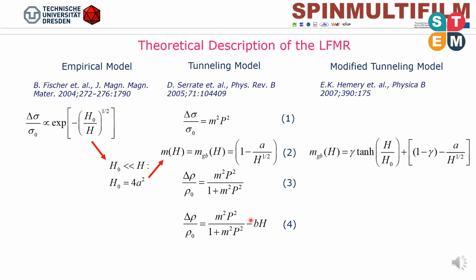Intragrain magnetoresistance is accounted for by adding a linear term, equation 4. This linear term is typically large near the magnetic ordering temperature. In the limit of small fields compared to the magnetic field parameter H sub 0, the empirical model coincides with the tunneling one. To improve the fit of the magnetoresistance data of pressed barium strontium ferromolybdate powders at low fields, a hyperbolic tangent function correction was added later.